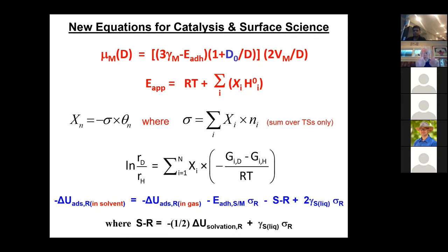And when you have dipole moments that point in the same direction next to each other on the surface, they repel each other. And so there's usually repulsive interactions that cause the heat of adsorption to decrease with coverage when you measure it in the gas phase or in ultra high vacuum. And so you see a big dependence of the heat of adsorption on coverage.